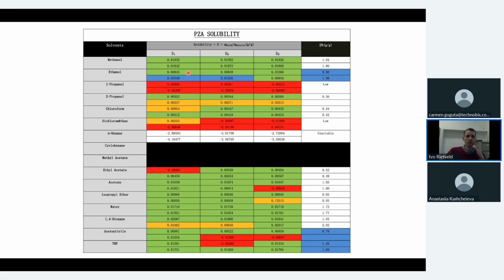What we obviously first started with, because you need all these crystals that I in fact already showed, was solubility tests in different solvents. I would say nowadays we would use the Crystal16 for this because that is what we have nowadays. But at that point in time, we still used students. Being at the university, that is an easy way out, so to say. But that allowed us to see which different solvents we could use for crystallization experiments. And after that, we got to which solution to use for which particular form that we would obtain, and then used cooling crystallization or slow crystallization, etc., at ambient temperatures to obtain our crystals.